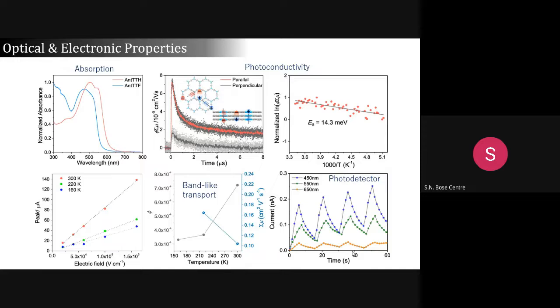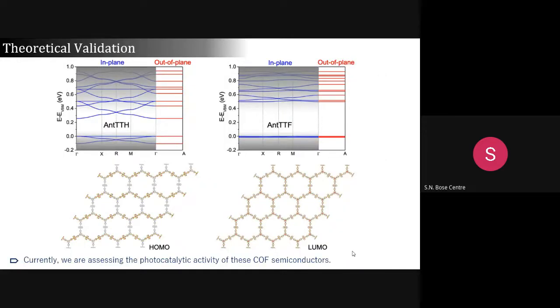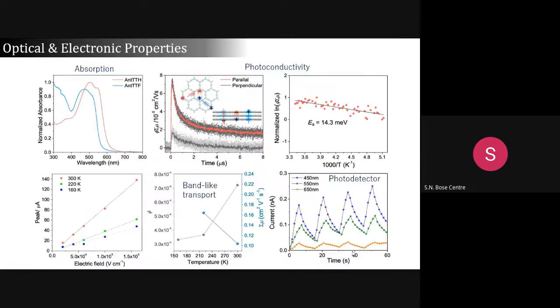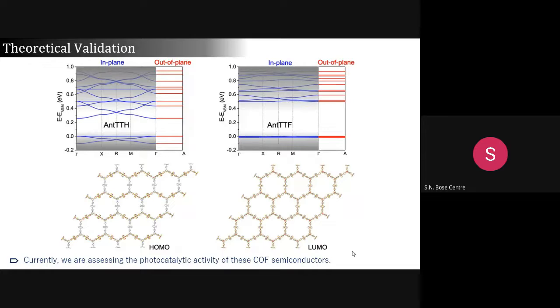If you take this film on an interdigitated gold electrode and just shine light, you will see an increase in current, even with room light. To understand this charge transport, we calculated the band diagram, and we found that in plane it has band dispersion. If we calculate that, the reduced mass will be almost 0.64 m0, whereas in the out-of-plane direction there is almost no band dispersion. So the electron will be heavier over there.